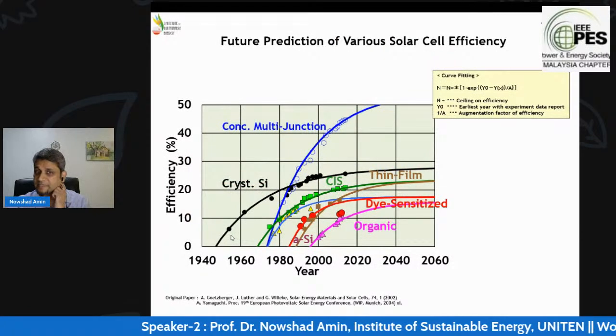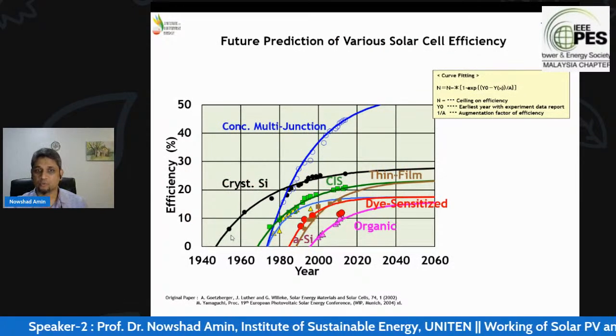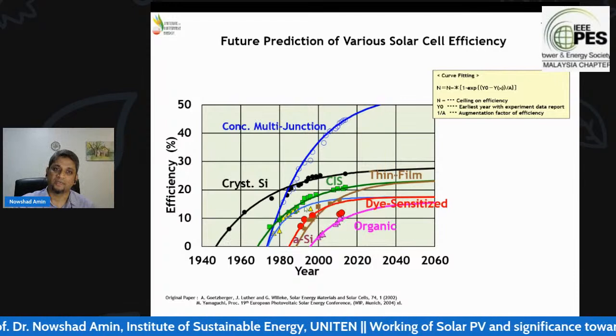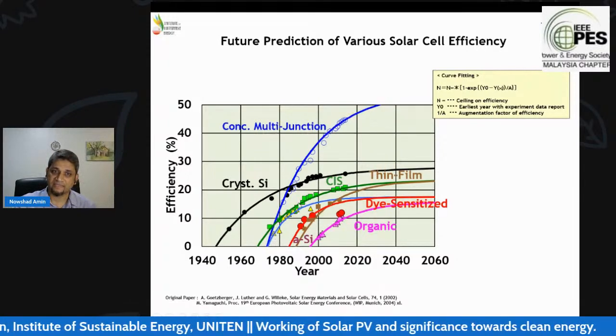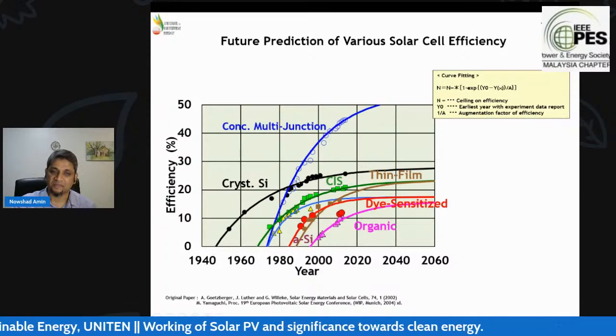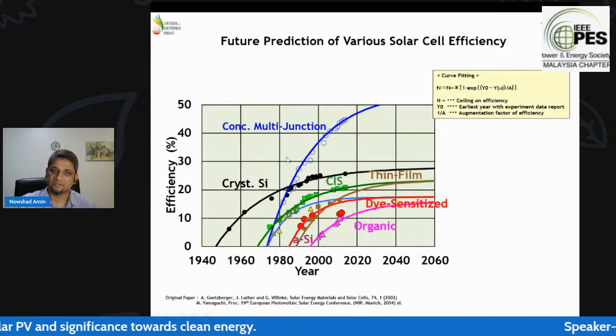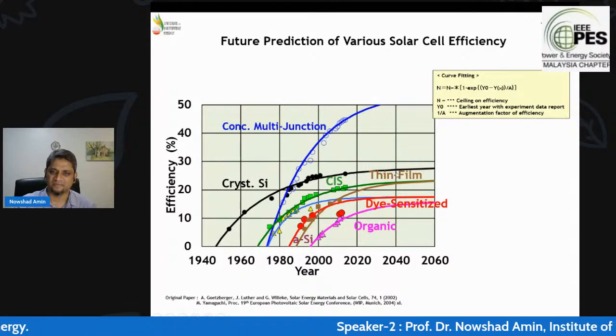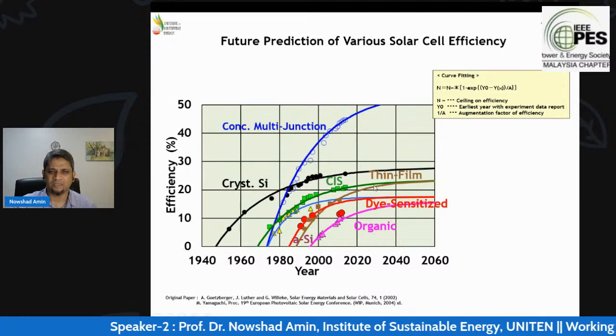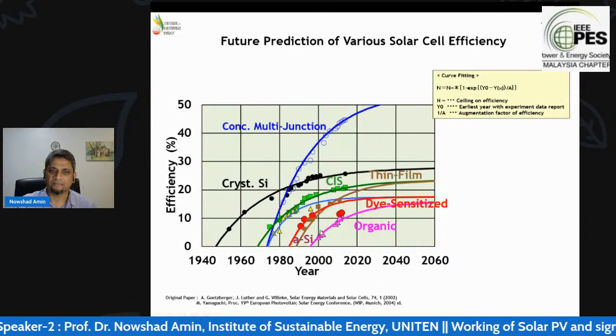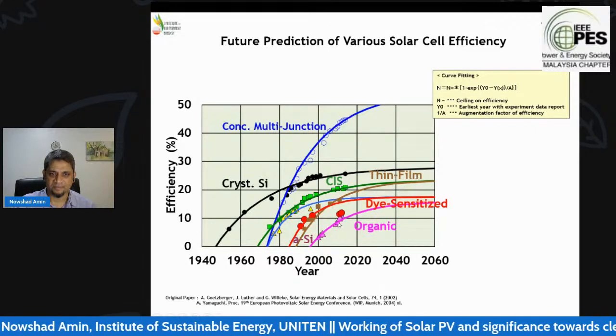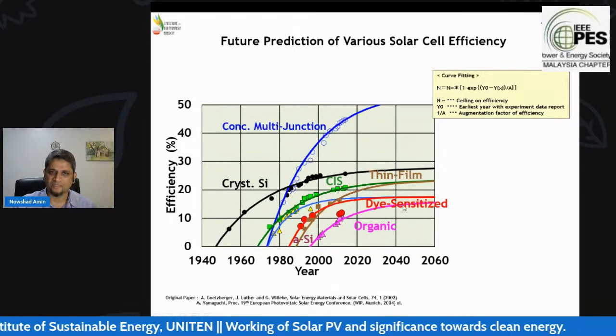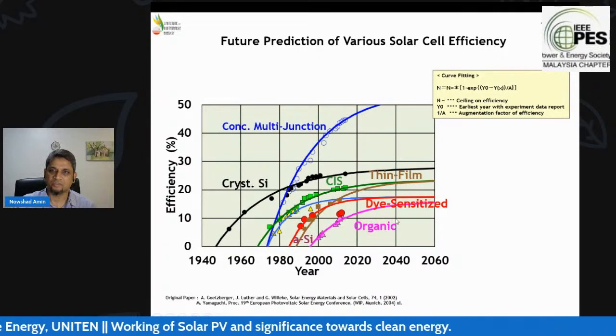So there is a prediction. There was a prediction, I think, almost 20 years ago, of how far we can go. The predictions are shown by the solid lines, and the reality is shown by the dotted points for each technology. For example, crystalline silicon is almost following the trend and is almost saturated, in fact, for single junction configuration. For CIGS also, it's roughly there. Thin film, other options, amorphous silicon also almost saturated, in fact. Dye sensitized, we do not see any kind of trend.